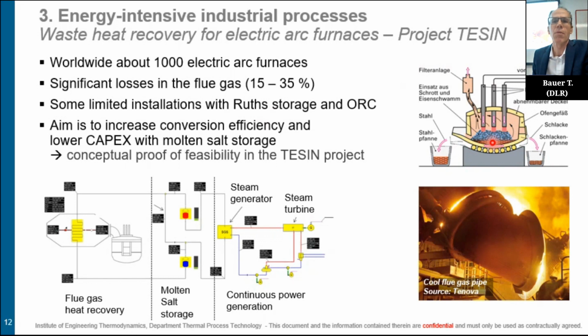And then once the scrap is molten, you pour the steel out, and you have some slag as well in the process. And you have a lot of flue gas here. The typical way is that they don't use the heat in the flue gas at all, and the heat in the flue gas is between 15 and 35% of the heat input. A typical furnace maybe has 100 megawatt of electrical power. So you can imagine that you have a lot of flue gas heat here.